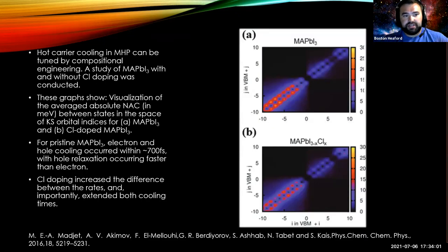And so some studies were conducted on them, and they found that hot carrier cooling in the perovskites can be tuned with compositional engineering. So a study of the methylammonium perovskite with and without chlorine doping was conducted. These graphs show visualization of the nonadiabatic coupling in millielectron volts between states in the space of the KS orbital indices for the pristine and the doped system.